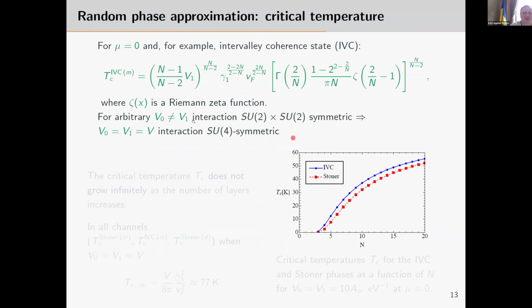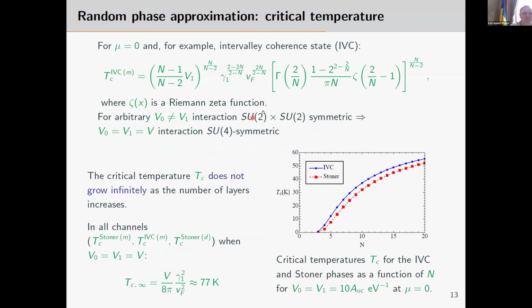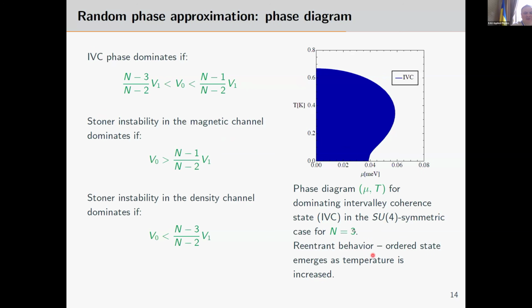And examples of the main results that we calculated, for example, the critical temperature as a function of the number of layers. For example, this is the case of the random phase approximation. We calculated the phase diagram. An interesting feature is reentrant behavior. So we increase the temperature, and the intervalley, so-called coherence phase appears. This is a very interesting feature, reentrant behavior.